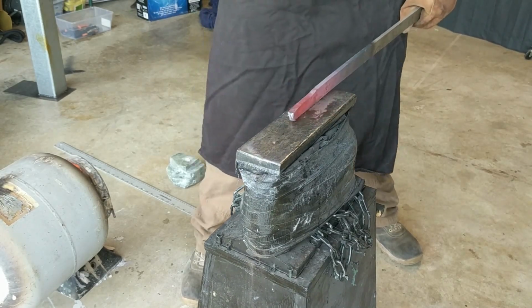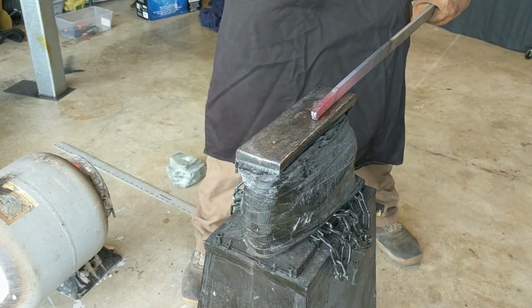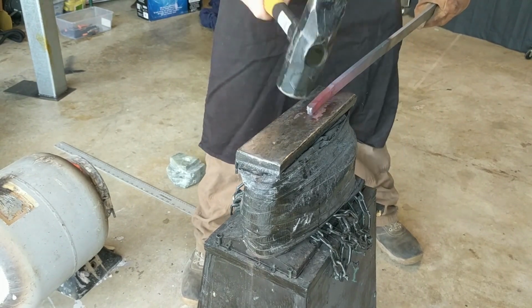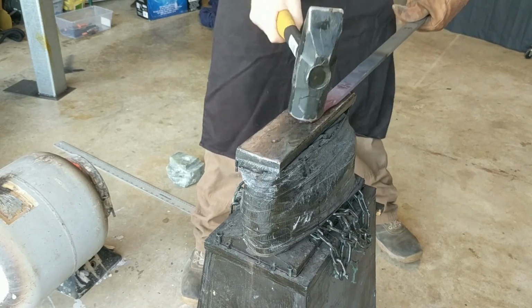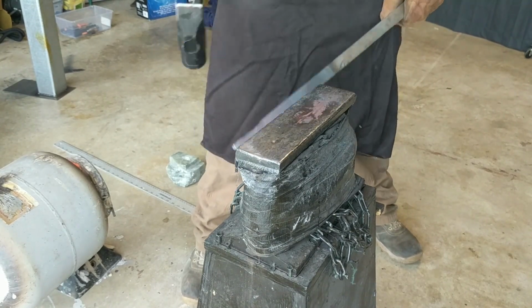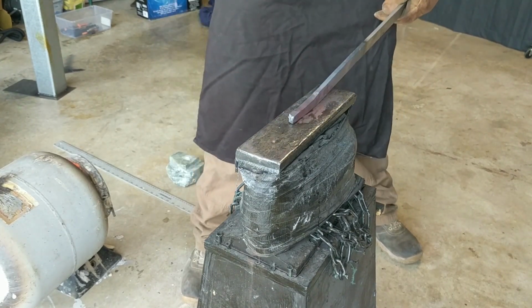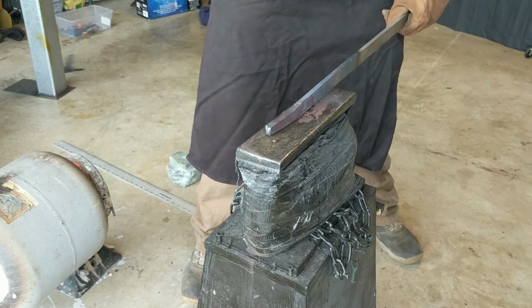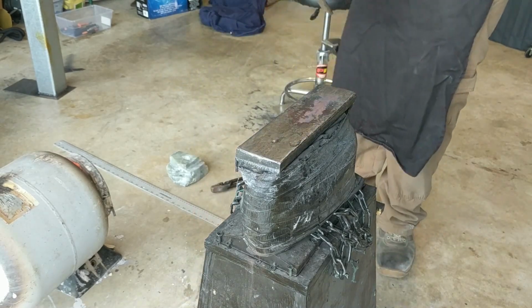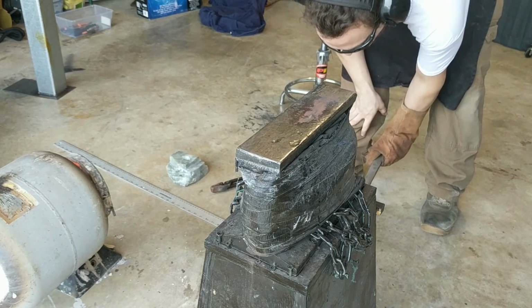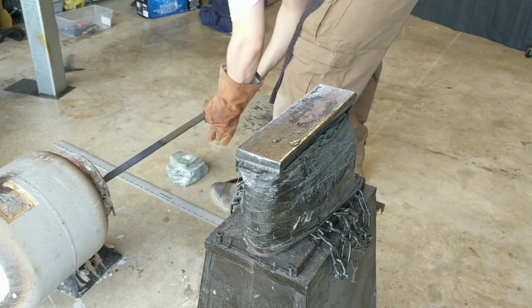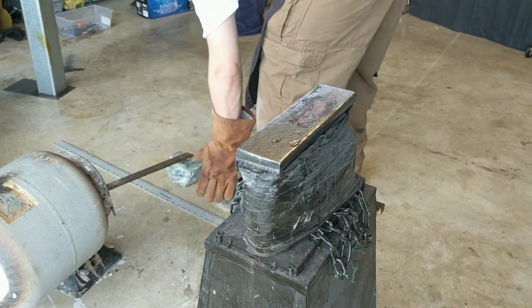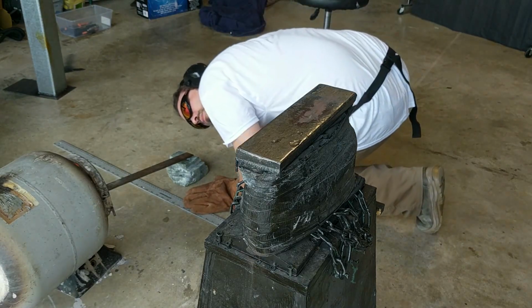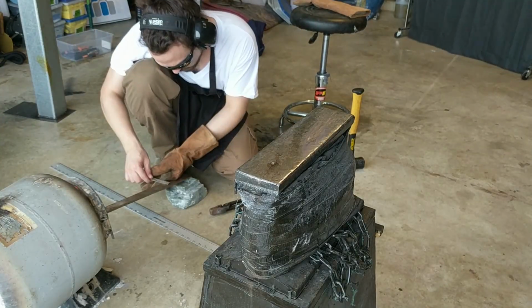You'll see that I've put some water on the face of the anvil here, which is an old Japanese swordsmith trick. The steel is so hot that it doesn't immediately touch the liquid water, forming instead a vapor jacket in a process called the Leidenfrost effect. When you bang the steel into the anvil, you collapse that jacket and the water boils explosively, blasting off the forge scale, aka magnetite, aka oxidized iron that forms on the surface of the steel in the forge. This basically just keeps the thing a little bit cleaner, prevents you from having to get it out later as it gets banged into the work itself.